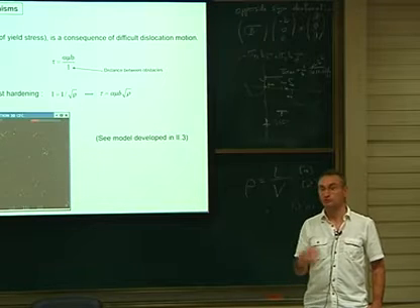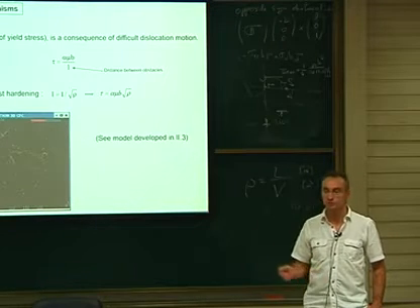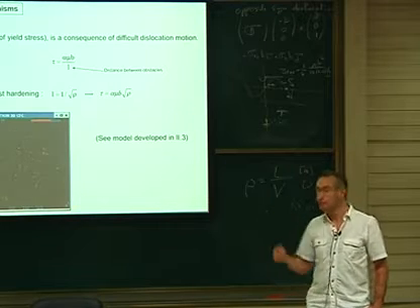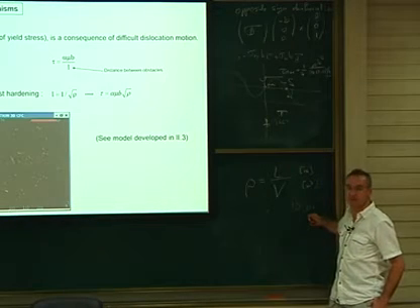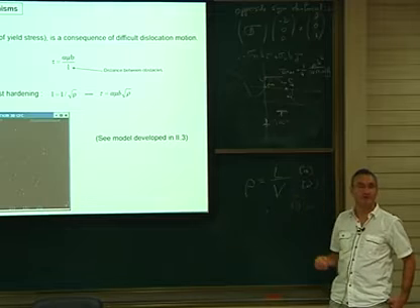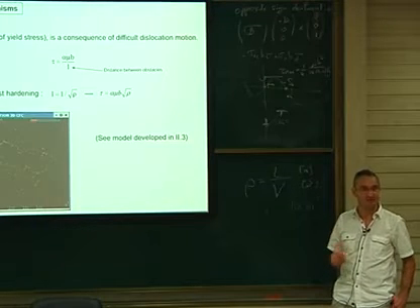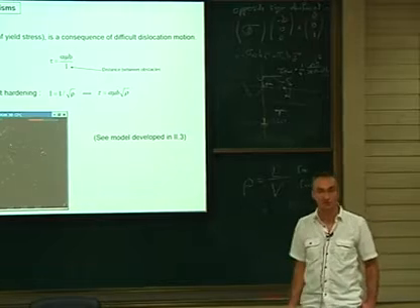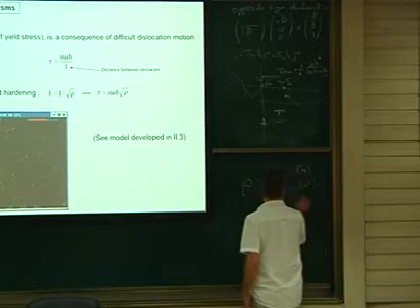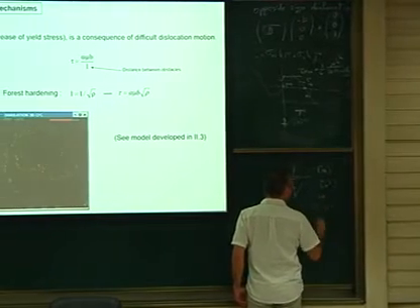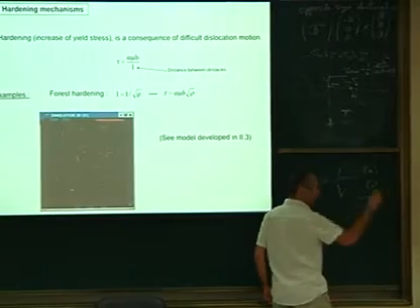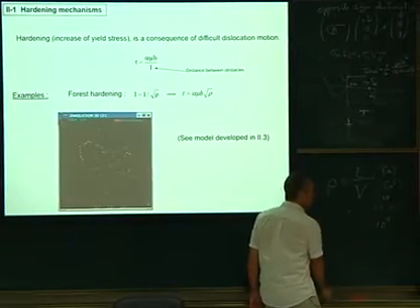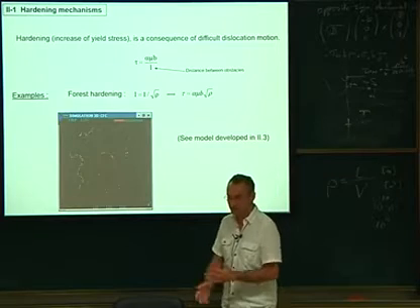Yes, 10 to the 10, 10 to the 12. These are good numbers, typically. It could be as low as 10 to the 8, I would say, for very good material. Be careful of the units. Sometimes people write it in centimeters, so this also changes the order of magnitude of the scale. But 10 to the 8, 10 to the 12 is a normal value that we can find in TEM observation. Let's put 10 to the 10, and 10 to the 12; maybe you can go higher, it could be 10 to the 13 and so on. Maybe tomorrow we'll compute some maximum value for dislocation density.